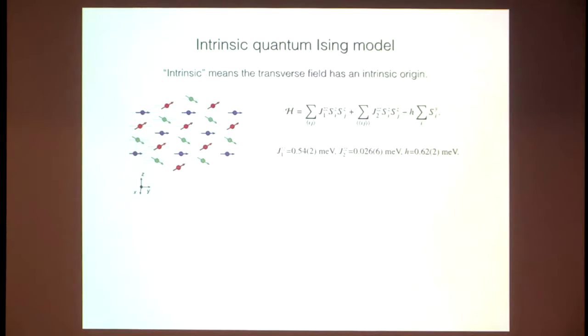So it has to be confined. Then you have dimer plaquette order. If you go back into spin language, you have this magnetic order. So in terms of the original spin language, the system has some kind of order. It's some kind of three sublattice magnetic order.